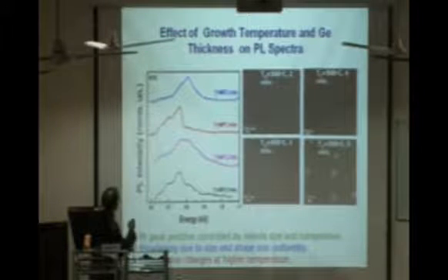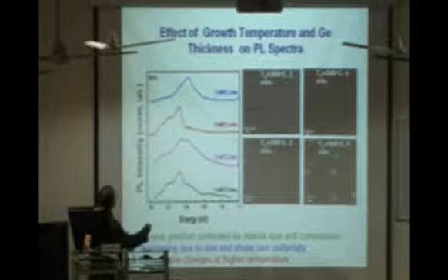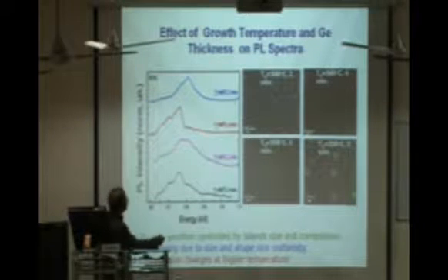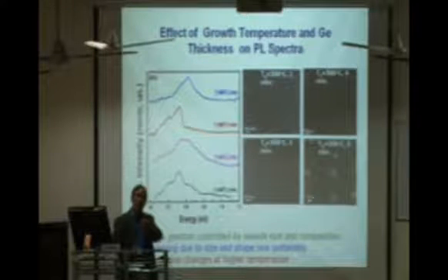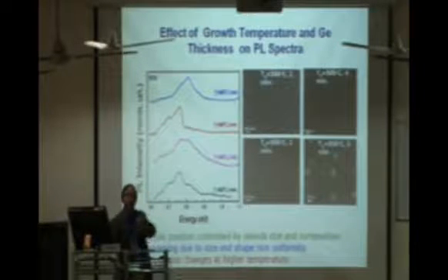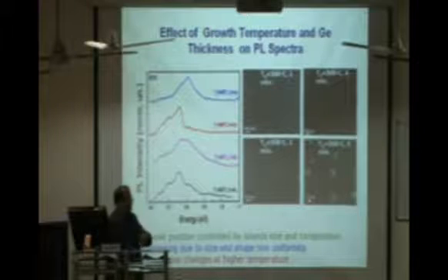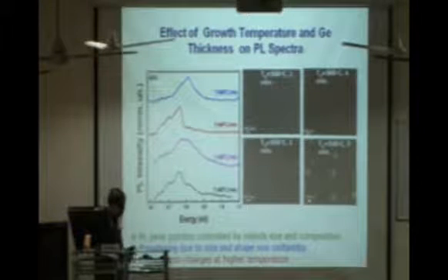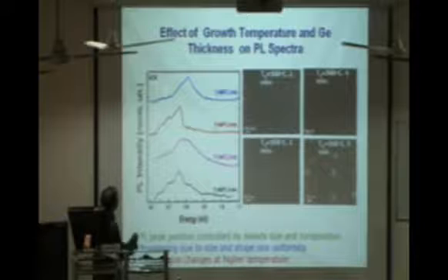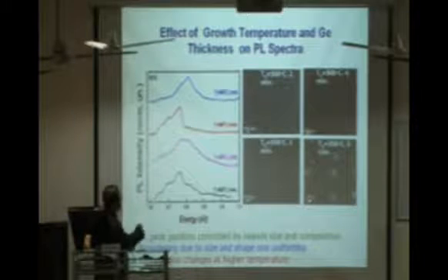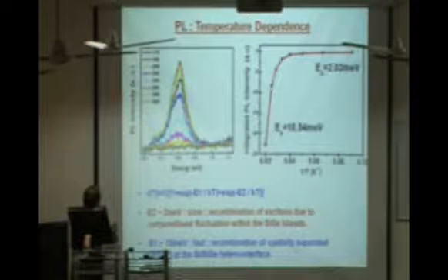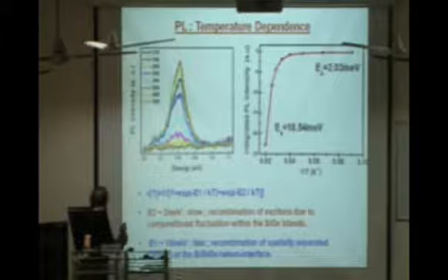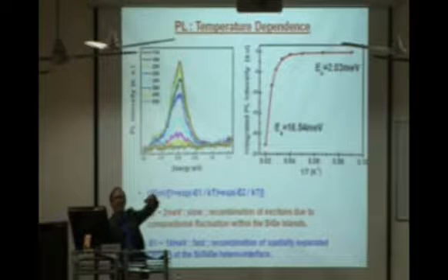What you want to show is that this emission energy, as you see, shifts as a function of the size of the material. That is called the quantum size effect. That is one direct proof that if you get a size-dependent shift of the luminescence or the optical absorption or emission peak, you know that this material has entered the so-called quantum region. Only thing, as you see again, this is very broad because of the size distribution of those quantum dots. In fact, this luminescence typically exists only up to about 40 Kelvin or a maximum of 50 Kelvin, because the exciton binding energy is very, very low.